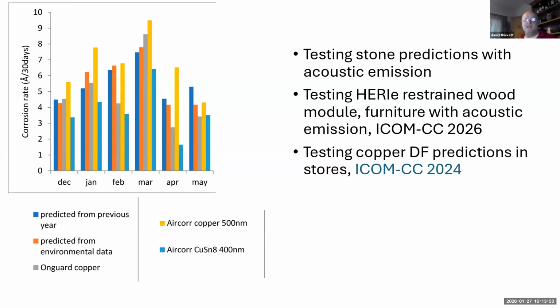And there's not a bad correlation between the blue bar and the grey bar, as good as you could probably hope. Within the project, we've been testing predictions for stone with a method called acoustic emission. We're hopefully about to publish in ICOM-CC testing the HERIe restrained wood module with furniture and acoustic emission. And we've previously published testing the copper damage function with stores.